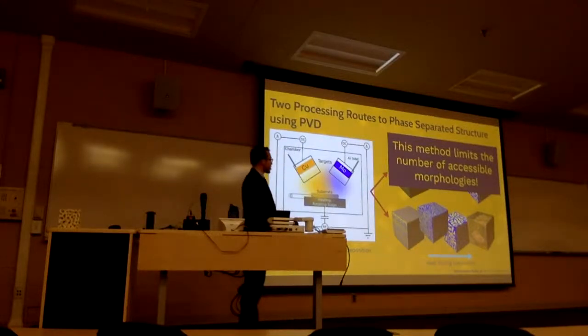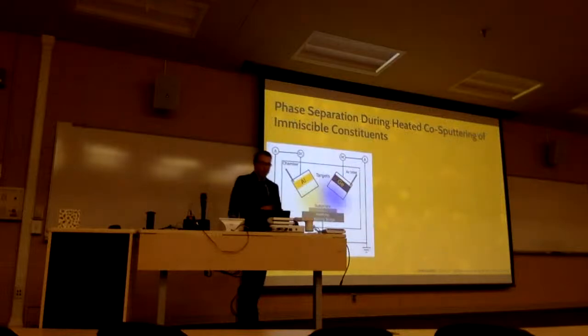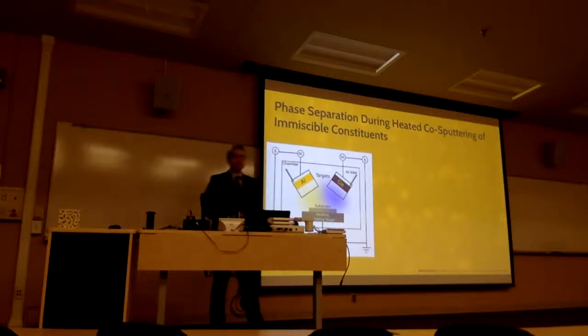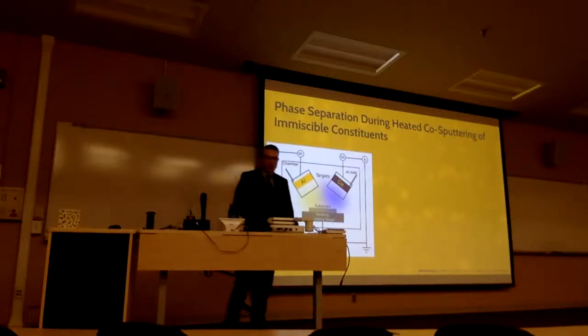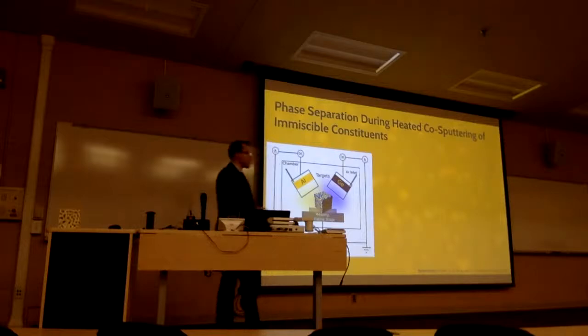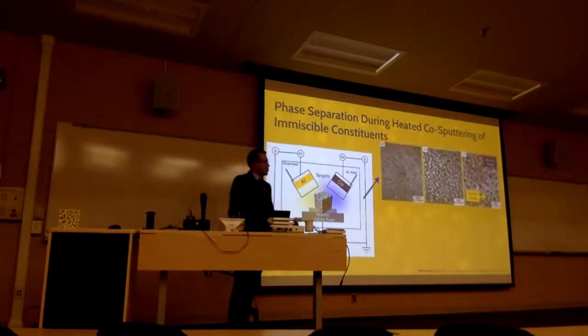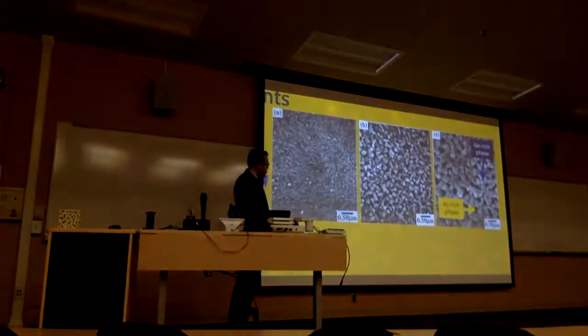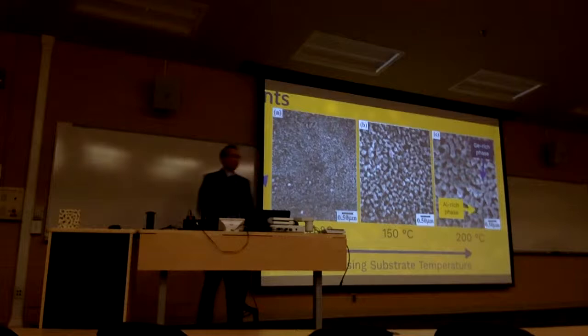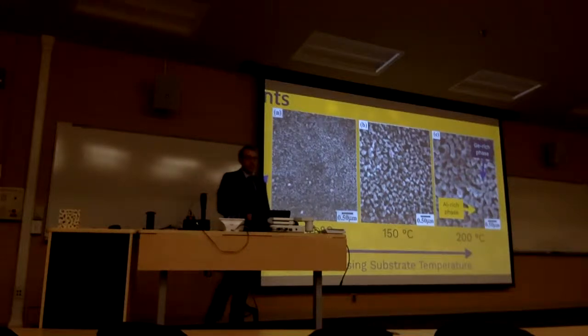We've actually seen this in literature as well. So actually led by one of my committee members, Dr. Michael Atzman, led a study where they co-deposited aluminum germanium onto a heated substrate. And what they found was a bicontinuous-like morphology. And here are the resultant morphologies. So you can see the aluminum-rich and germanium-rich phases highlighted here. And what they did was they varied the substrate temperature during deposition.